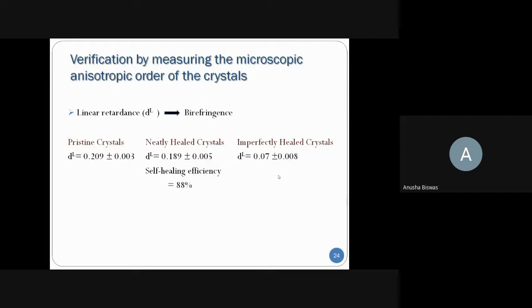Here the delta L values for these three crystals are shown. We can find that the delta L value for pristine and neatly healed crystals are quite similar, but in the case of the imperfectly healed crystal, it's almost one third that of the pristine one. So it denotes that the self-healing efficiency in this imperfectly healed crystal is actually less. All of these denote the imperfect recombination of the broken fragments in the imperfectly healed crystal, whereas the neatly healed crystal performed the self-healing property very perfectly.